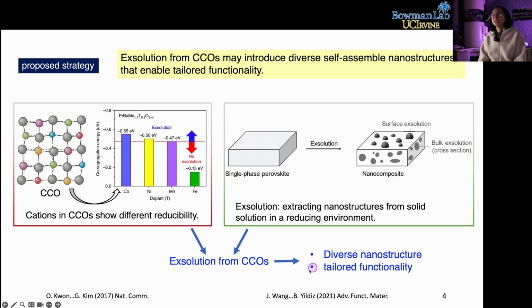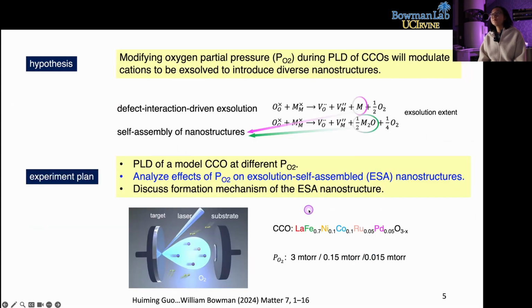So in this work, what I want to do is use a fixed component of CCOs and try to tune the exsolution extent to decipher the diverse nanostructures the exsolution can provide in CCOs. My hypothesis is that modifying the oxygen partial pressure during the PLD of the CCOs will modulate the cations to be exsolved to introduce diverse nanostructures. The oxygen partial pressure is closely related to exsolution extent. With stronger exsolution extent, more phases are exsolved from the matrix. These exsolved phases will self-assemble and grow during the thin film growth in the PLD. This process of making self-assembled nanostructures is what we call exsolution-self-assembly.